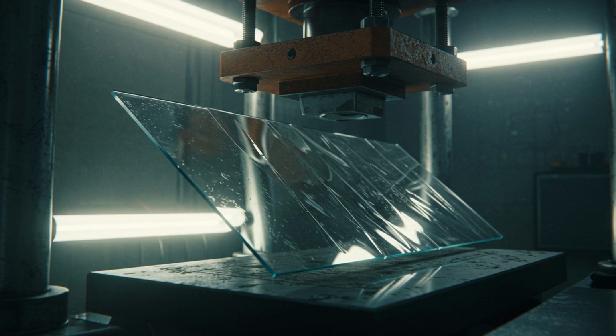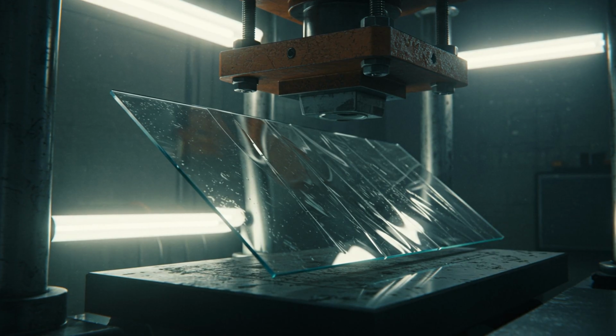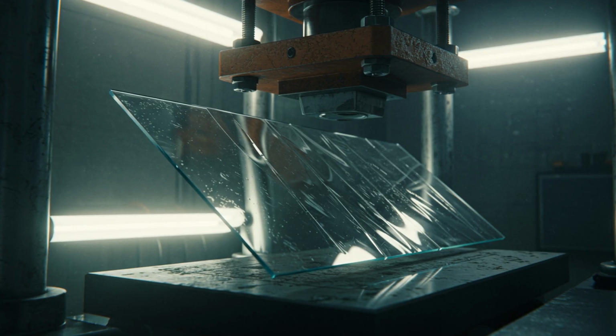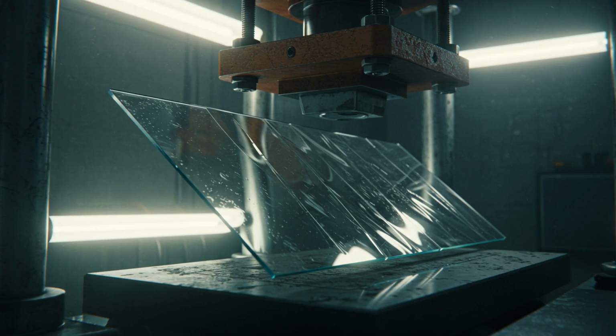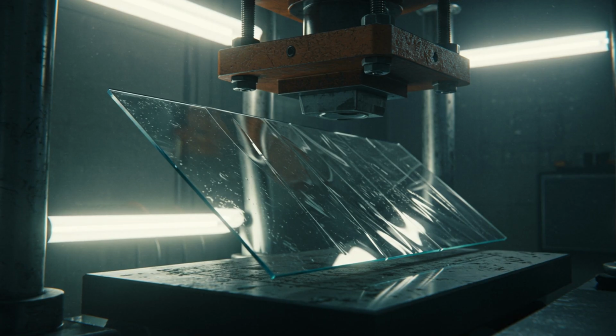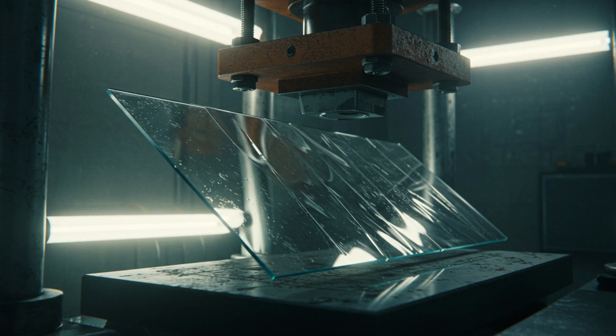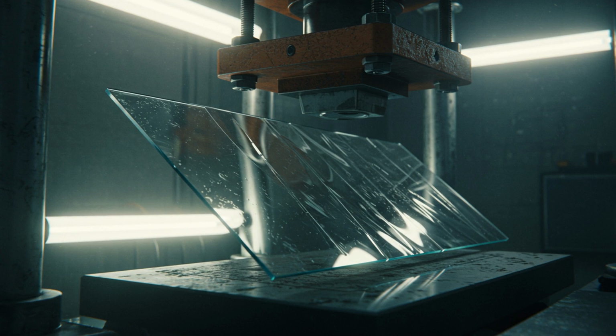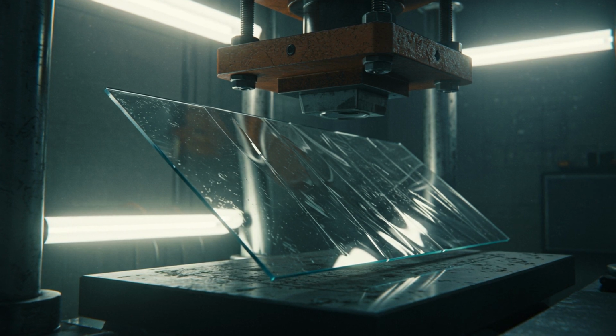as cullet. For mirrors, we use salt spray tests, simulating years of exposure to bathroom humidity and cleaning chemicals to ensure the silver backing doesn't peel. We test thermal shock by moving glass from freezing to boiling temperatures in seconds. Only the most perfect sheets survive. Engineering glass is about more than just clarity. It's about the reliability of a material that we trust to hold back the wind at 60 miles per hour on a highway, or to keep the heat in during a sub-zero winter. From a pool of liquid tin to a flawless reflection, the journey of glass is a testament to human precision.